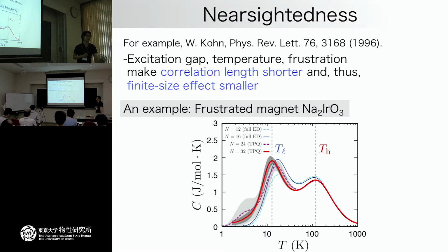It's not always so for frustrated magnets. For example, in Kagome and in triangular lattices, it's quite large. In this sense, in the Kagome system, the remaining entropy at low temperature is quite small. This is the reason why. I don't agree with that, because recently people have recognized that the specific heat is going to show again. If you measure the temperature dependence of the entropy, the remaining entropy is not so large in the Kagome. We have also checked it. Yeah, I know. Because in this case, more or less half of the entropy remains. I just mentioned that maybe this is a special case, but it's not always holding in frustrated magnetism.